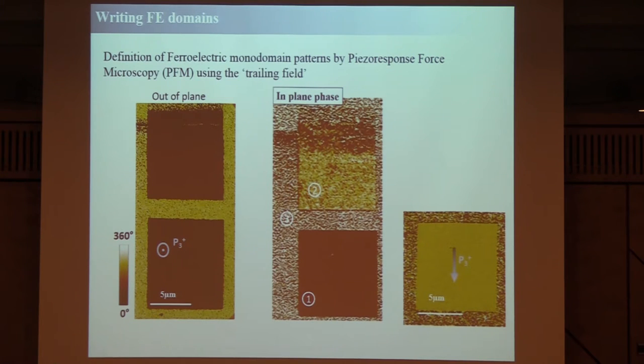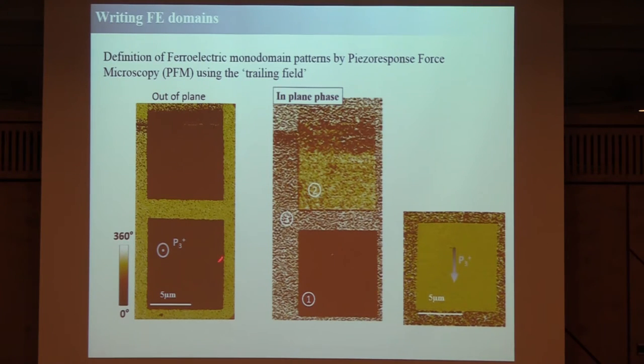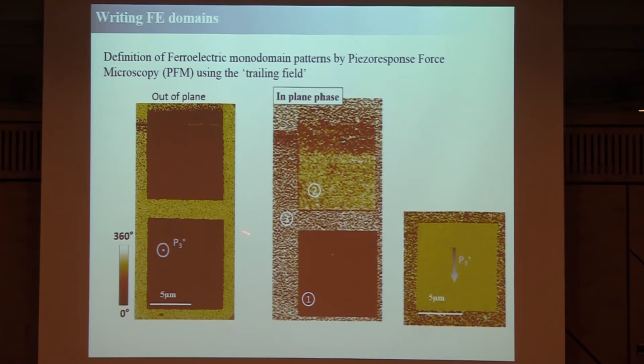The trick is to use the PFM tip to write single ferroelectric domains. This is a bit tricky since the polarization lies along the [1,1,1] directions, but there are ways to do it. We can write a single domain: a 10×10 micron region where P is constant, which we call P3+. In another region we attempted the same but it didn't work perfectly — we ended up with bi-domains, two polarization variants at ~100 nm scale. But let's focus on the single-domain region.